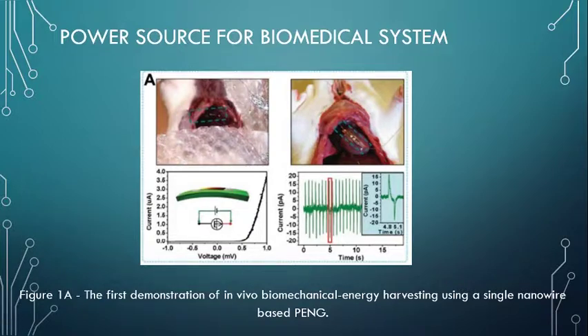By integrating multiple nanowires, the output voltage can be increased, and 4 zinc oxide nanowires in a series connection can produce an output voltage of 0.15 volts. Based on the same mechanism, Lee and others developed an implantable PENG based on a single zinc oxide nanowire to harvest energy from the heartbeat of a living rat. Besides energy harvesting, some crucial issues for in vivo application were also addressed in this work, such as the biocompatibility, toxicity, encapsulation, the anchoring, and the potential for active sensing of in vivo biological motions.